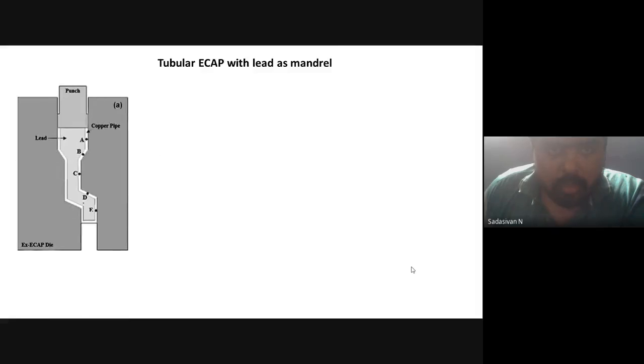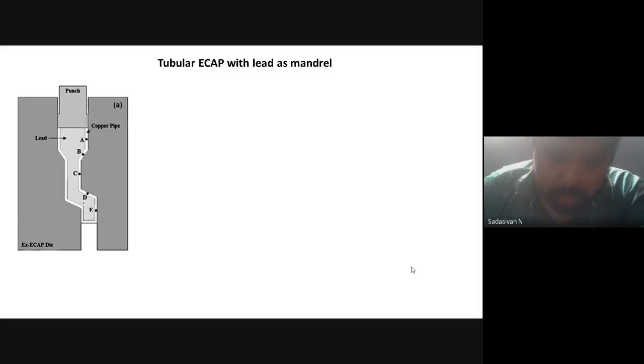The second method is an integrated extrusion ECAP, where a small extrusion happens before your ECAP. So there is one extrusion here, a small reduction in diameter, after which you can have one pass of ECAP and the next consecutive pass here. Here you have one shear, and the second shear is happening here.